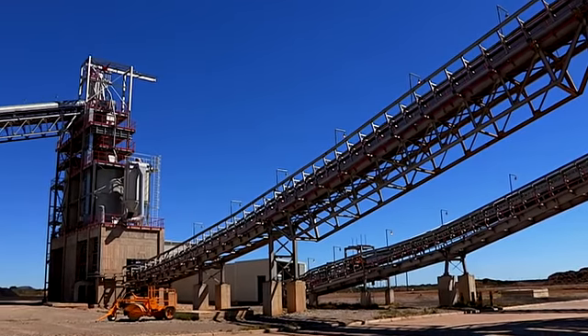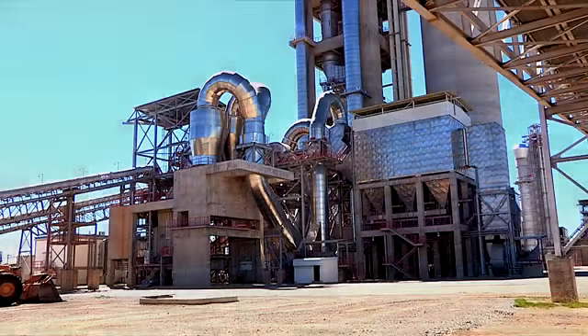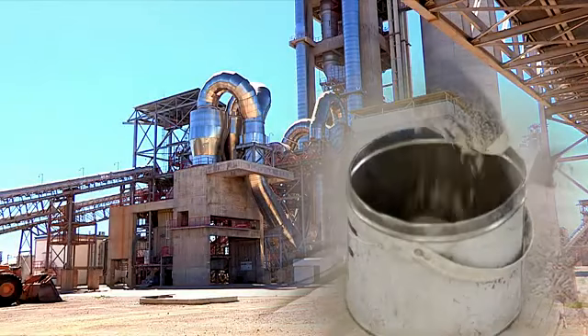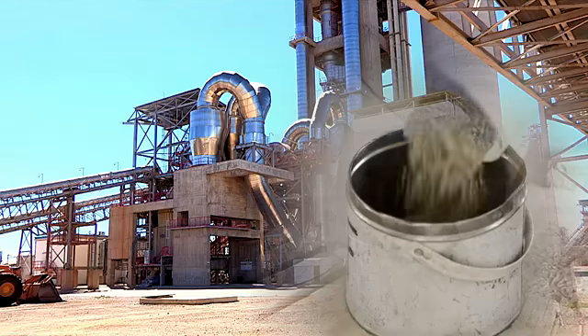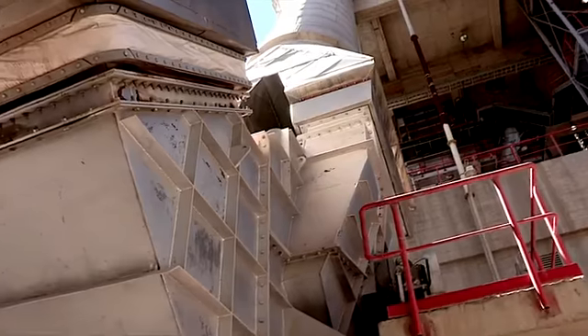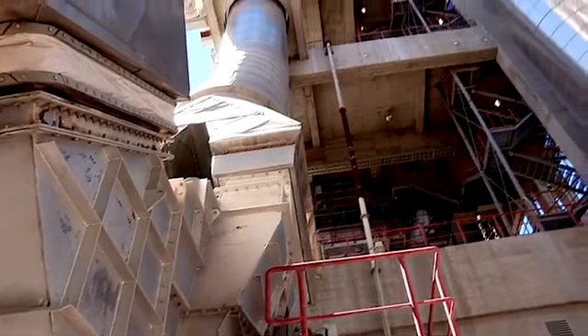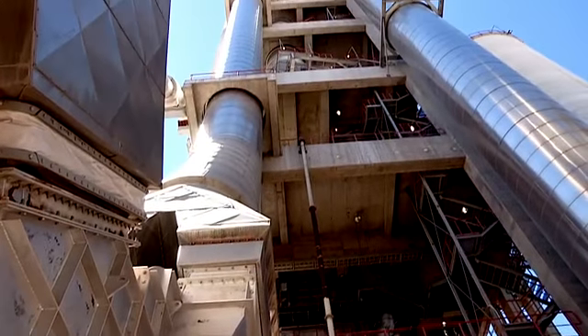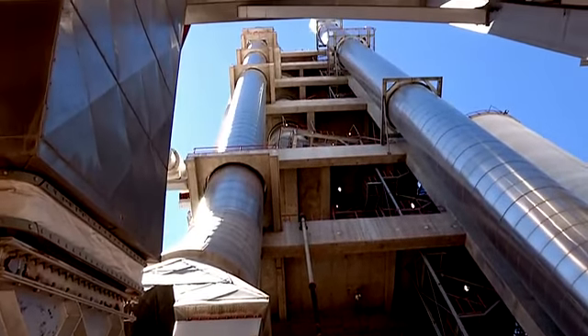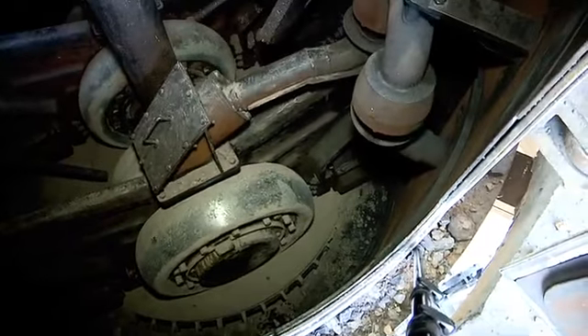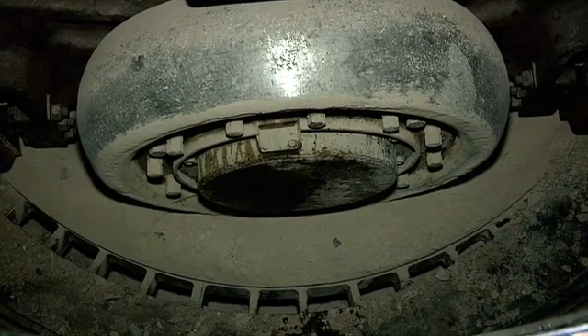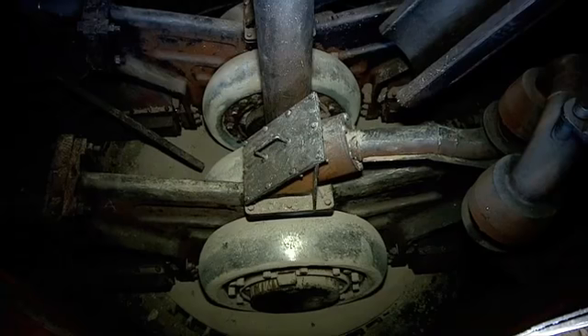Essential additives such as iron ore are added to the homogenized limestone, shale and marl material, and this mixture is then conveyed to the raw mill, where it is ground to a powder with the consistency of fine flour, known as raw meal. While being ground, the mixture is dried by means of the excessive heat generated from the pyro process. The materials for clinker production are milled using roller mills instead of the traditional ball mills. The roller mills save about 30% on the total electrical power consumption compared to traditional ball mills.